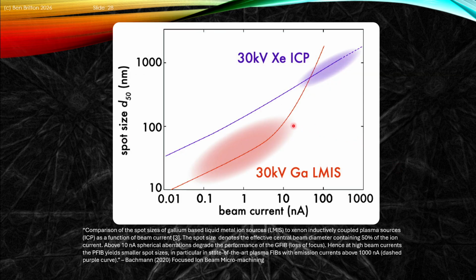Why do we use these different systems? We'll see a few things a bit later, but one that's important is that we can look at the so-called spot size, the D50, so that's 50% of the ions will be within this size. We can do this based upon the beam current of our system.